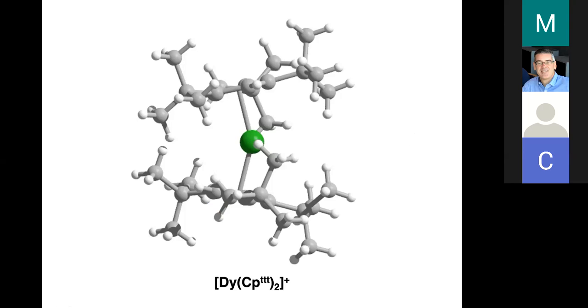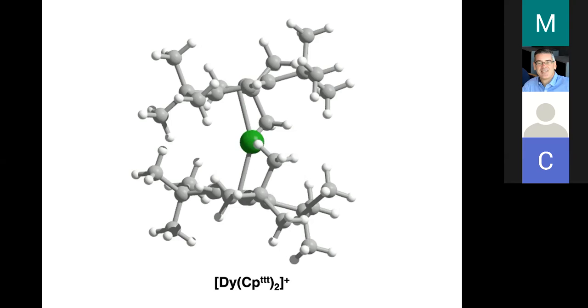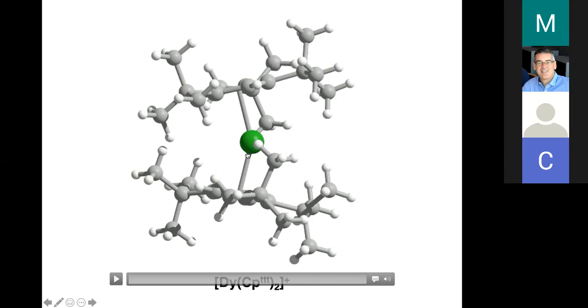And if you vary the substituents on the Cp ring, though, you can change things. There are two parameters that are really important here: the bend angle and also the distance between the carbon and the metal. The closer that is, the larger the M sub J splittings should be. And it turns out the more linear, the more axial the preference for the moment is.